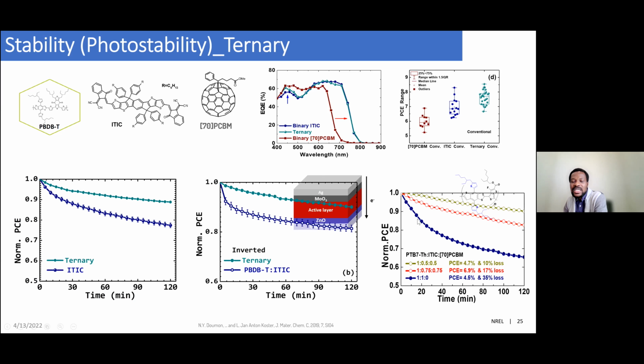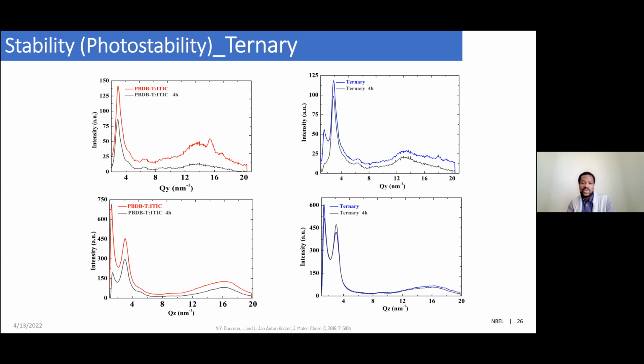With the ITIC binary blend, you can see that the degradation was very much pronounced. But when you begin to play with 70 PCBM, introducing it and forming a ternary blend, you can see improvements both in efficiency and the device stability, which are good news. And that also led us to really understand what is happening in the system.